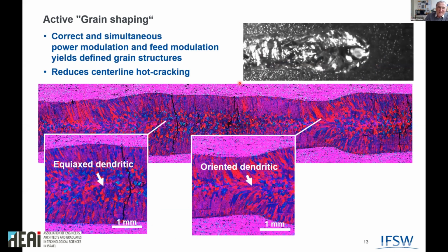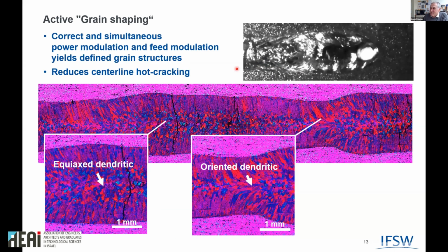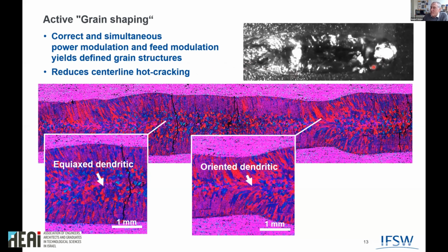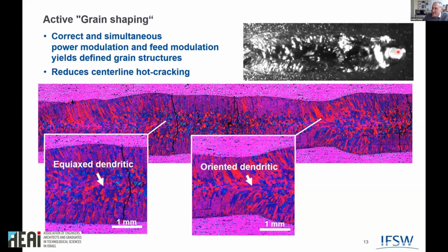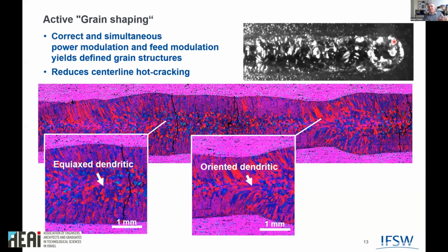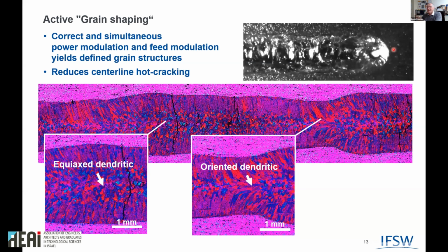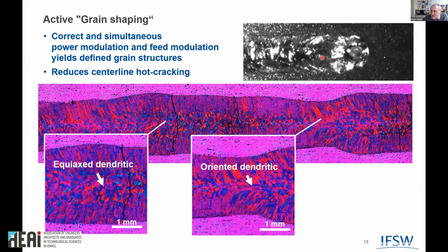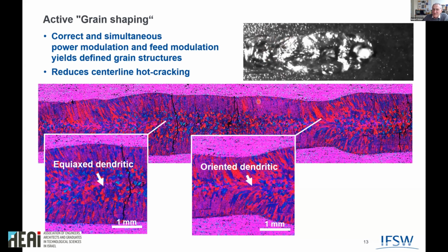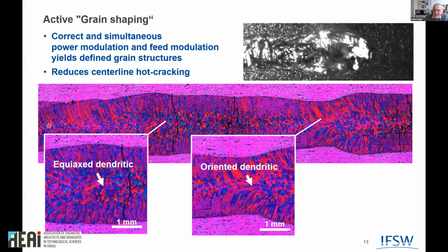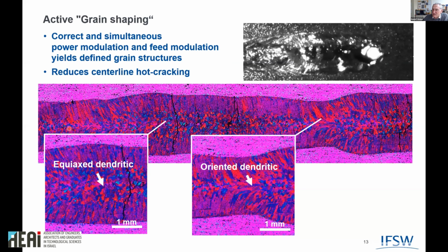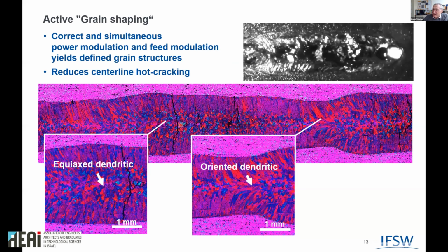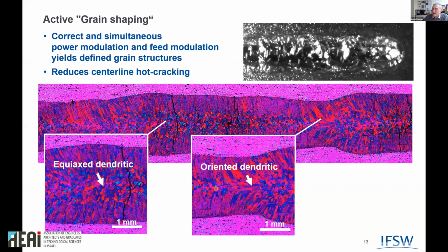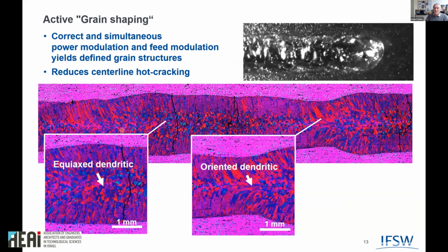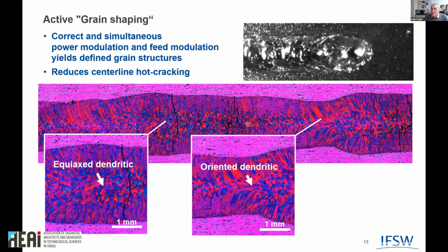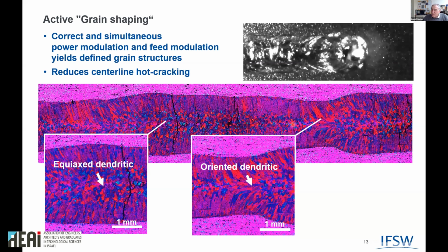And of course, one can go further. The next step, in addition to just wobbling, is to also make power and feed modifications, which means when you get slower, you decrease the power. When you get faster, you increase the power, which also changes the solidification conditions here drastically. And you can see that we could even achieve that in the middle we have no equiaxed grains, then we have a wide area of equiaxed grains, and again, back to no equiaxed grains. So this is the close-up. By doing this, you can even change the material properties while welding. And if some crack might occur here, we might stop it by changing the material.